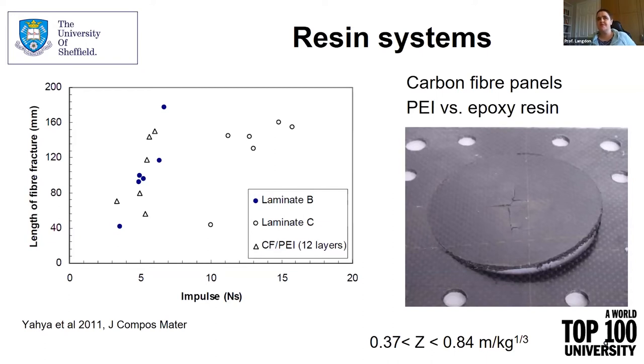The photograph shows the carbon fibre panel has sheared around the boundary edges and has some cracking in the centre. But apart from this damage, the permanent displacement of the fibre reinforced polymer isn't visible. The disc appears to be flat. Because of the elasticity in the polymer material, understanding the transient behavior would be critical. But at this point in our test career, we didn't have the ability to measure the transient deformation of a system such as this one.